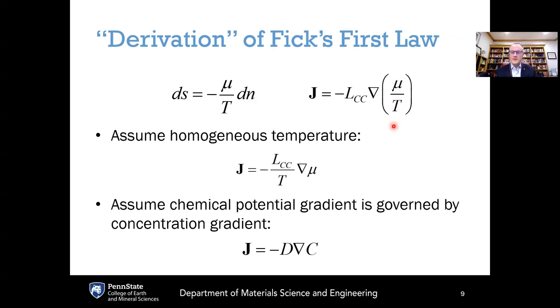Now we have to make a couple of assumptions to go from this formulation to Fick's first law. The first is that the temperature of the system is homogeneous. So we need to assume that the temperature is the same throughout the system. And if we do that, this 1 over temperature can be pulled out in front of the gradient of the chemical potential. The next assumption is to assume that this chemical potential gradient is entirely governed by the concentration gradient. So in other words, this gradient of the chemical potential is just equal to some constant of proportionality times the gradient of the concentration. Of course, in reality, there are other parts of the chemical potential that may influence actual diffusion, but in order to get